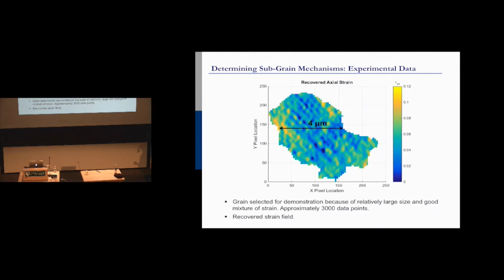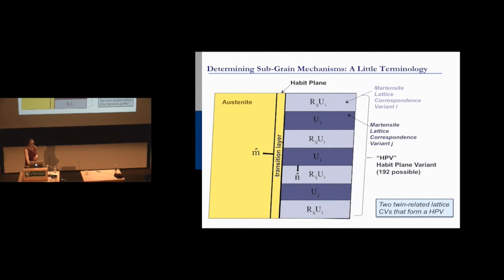But we picked a grain that had about 3,000 strain values in it, and we looked at strain as an extent of transformation. And to convince you that we can actually pull out the exact mechanisms of what's happening inside of each grain, I'm going to go over just a brief terminology, is look at these different correspondent variants. Everything's symmetry related. So the purple side are the different correspondent variants. So maybe this light purple is this tetragon, and the dark purple is this tetragon, and that's their twin, like we showed before. So you've got one correspondent variant, one tetragon up here, and it's twinning with another one.